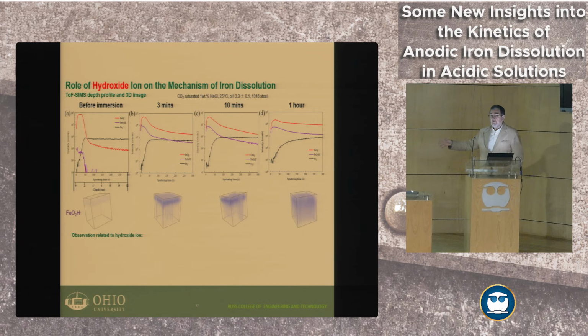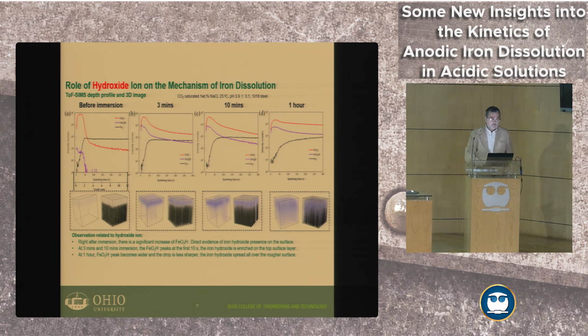It is a surface species. This iron hydroxide is a true surface species detected by ToF-SIMS. It's not just an imagination of those electrochemists that had to come up with something. It's true. It is there. All right, cool. What about putting it all together? And here you can see, initially the surface is there. There is no hydroxide, a bit of oxide there to start with. And after a while, hydroxide develops and basically is there all the time. Here black is iron, purple is hydroxide. So you have essentially the layer of hydroxide always during corrosion on the top of iron.